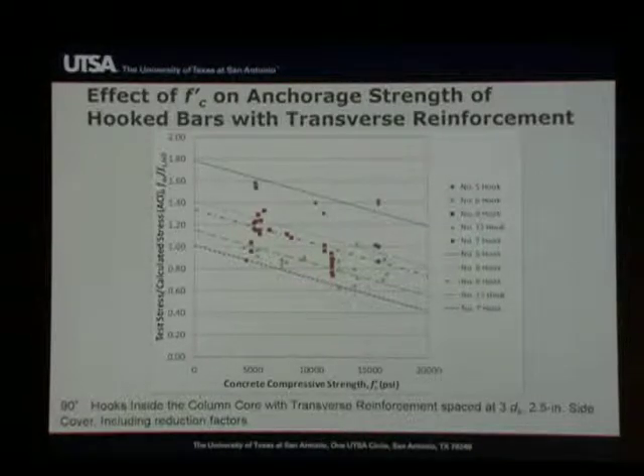We see the same trend where we have a very large degree of conservatism. You know, we're way safe with the number 5s, no problem over there. In some ways, we're over-designing the number 5s. But when we start to get into the larger bar sizes, 7s and 11s, well, here we have less confidence because we have a much lower number of data points. So you see some not so evident trends, but the larger bar sizes do tend to have a significant number of tests in the unconservative regions, even when we use transverse reinforcement.